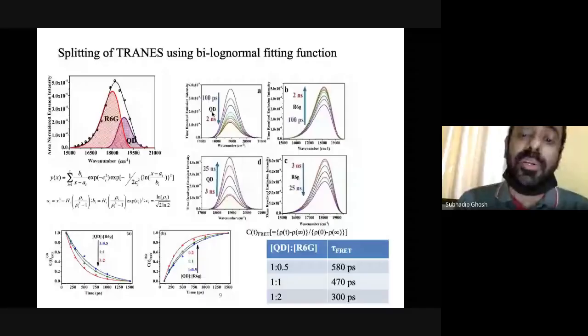In the bi-lognormal fitting, we fixed the peak positions, one corresponding to rhodamine 6G and another to the quantum dot, and we split one spectrum into two spectra. In two individual windows, we plotted all the spectra as a function of time. This portion corresponds to the quantum dot, and this corresponds to the rhodamine 6G portion. You will find as time progresses, the emission intensity decreases.